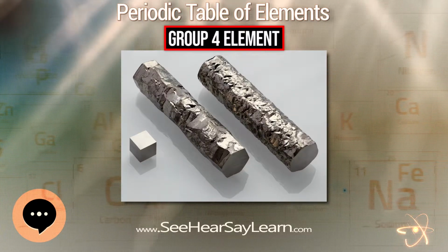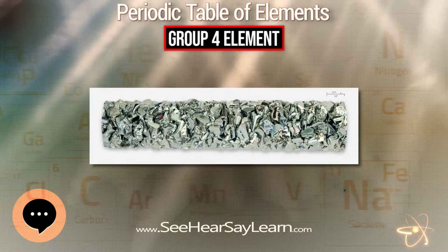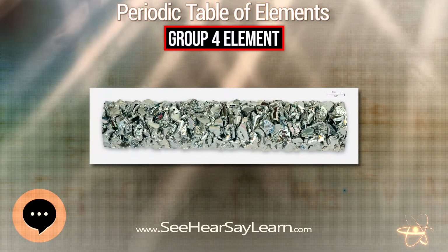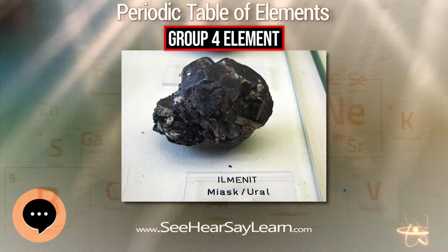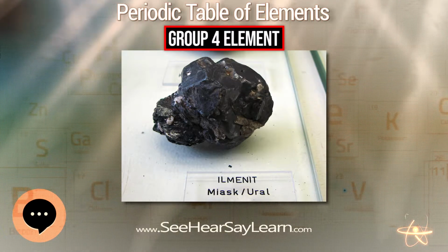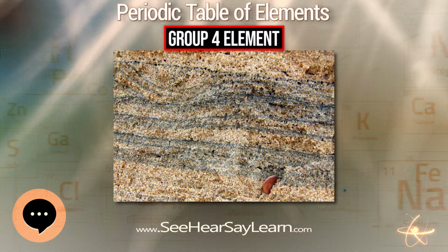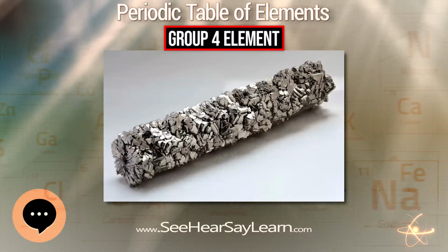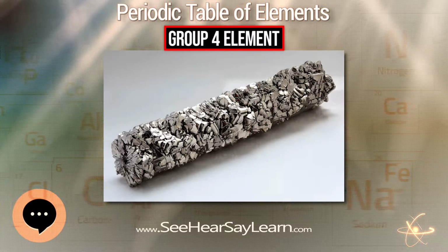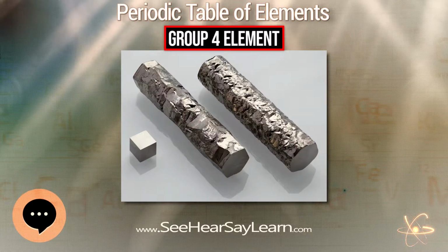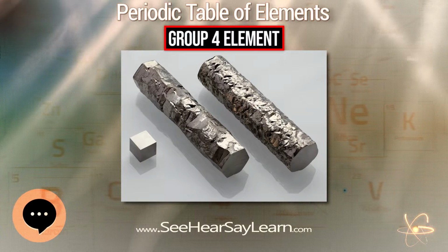Further purification is done by a chemical transport reaction developed by Anton Eduard van Arkel and Jan Hendrik de Boer. In a closed vessel, the metal reacts with iodine at temperatures above 500 degrees C, forming metal iodide. At a tungsten filament of nearly 2000 degrees C, the reverse reaction happens and the iodine and metal are set free. The metal forms a solid coating on the tungsten filament and the iodine can react with additional metal, resulting